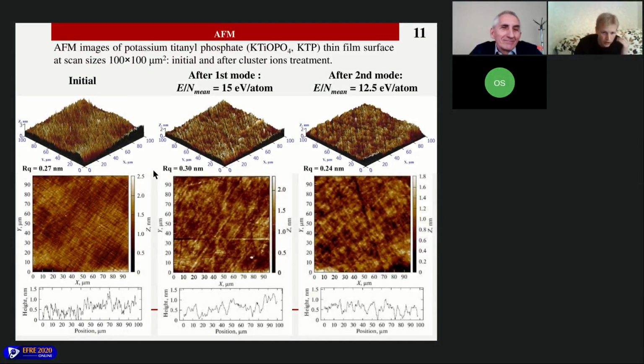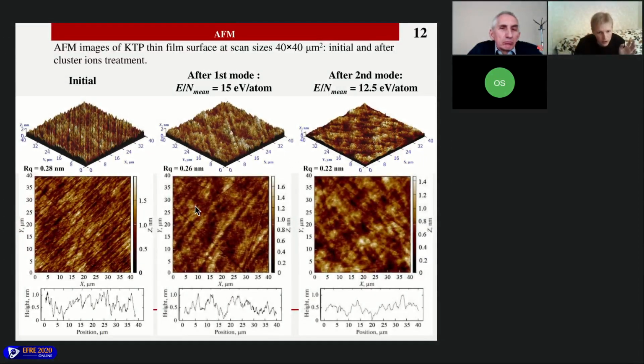Here you can see atomic force microscopy images before and after cluster ion treatment. At large scale, 100 by 100 micrometers, we see a slight change in roughness after processing, but the two-dimensional images and surface profiles show smoothing of the traces of mechanochemical polishing, which is especially noticeable at 40 by 40 micrometers.